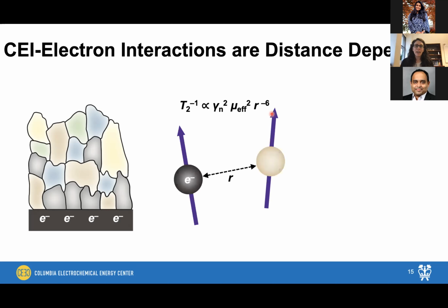The reason for that is that these unpaired electrons can actually couple to nuclei of interest in our interface. This has a distance-dependent effect, and it impacts different NMR parameters in our experiment. So the NMR parameter that we're going to care about most in the experiment that I'm going to talk to you about today is something called T2. This is our spin-spin relaxation. And it has this distance-dependent effect.